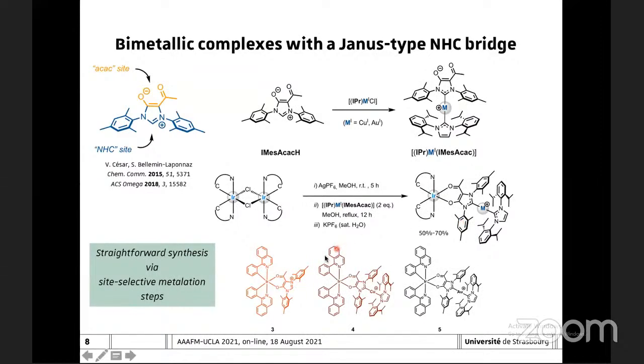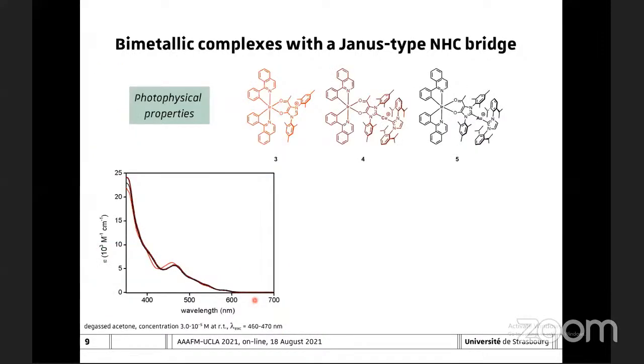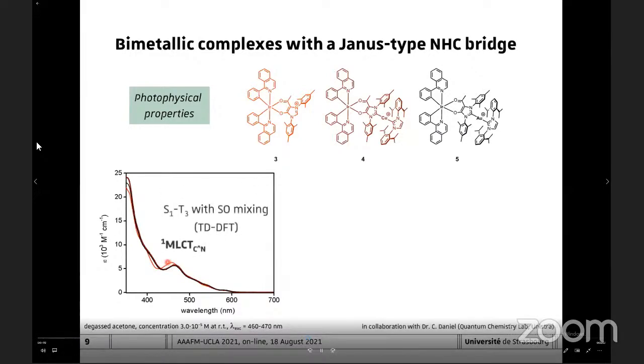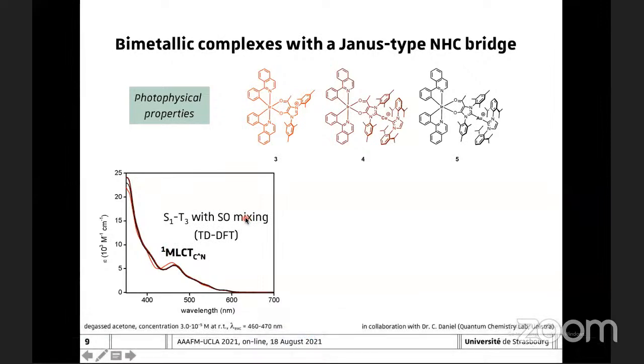So we were able to straightforwardly prepare a series of heterobimetallic complexes, and here, just for sake of time, I will present just two of those, in particular compounds 4 and 5, and we can compare those with the monometallic counterpart, compound 3. If you look now briefly at the photophysical properties of those compounds, we can see that along the series 3, 4, 5, we have very similar absorption spectra. In particular, for 4 and 5, the absorption spectrum is basically superposable. We have just a tiny, very small hypsochromic shift for the singlet metal to ligand charge transfer band for compound 3. Thanks to the DFT calculations, including spin orbit effects, we are also able to associate that band to the singlet metal to ligand charge transfer involving the cyclometallated ligand.